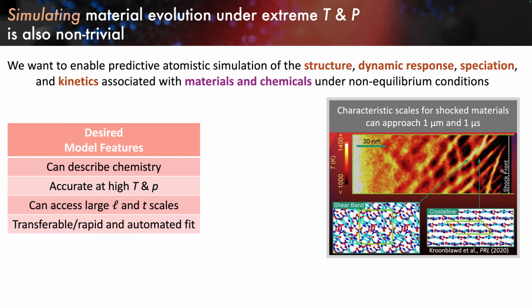So if we want to understand that process, we need simulations large enough to resolve these several tens of nanometers long and roughly 10 nanometer wide features. At the same time, we need our model to describe the atomically resolved chemistry happening within these features.